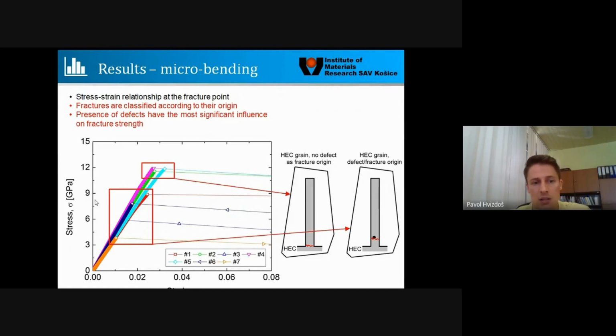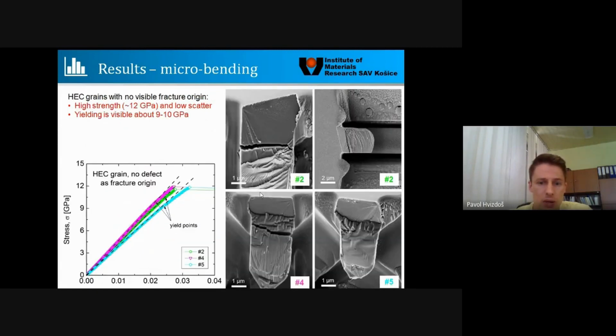Those which have lower strength correspond to those cantilevers which failed on some defects, as I mentioned earlier. Those defects were located somewhere farther from the fixing and therefore fractured a little bit earlier, because they act as a stress raiser and increase the stress, and therefore the cantilever failed. So we basically got two groups. There was one group with no visible fracture origin, those which failed at the beginning, I mean at the fixing of the cantilevers.